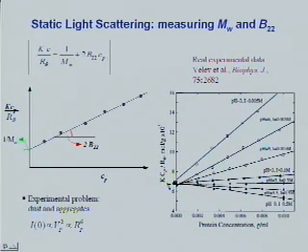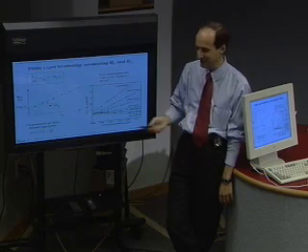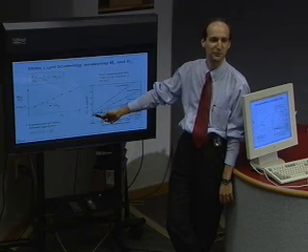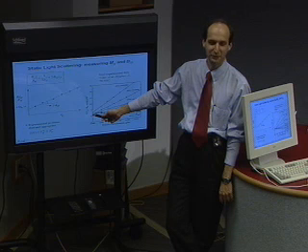And if these curves didn't cross... this is just two parameter fits. So it's not that I have adjusted this point. I was lucky that they crossed there. If they hadn't crossed here, I would be in deep trouble, because if this value was not comparable to the molecular weight of the protein, it would mean that my data is not going to be reliable.